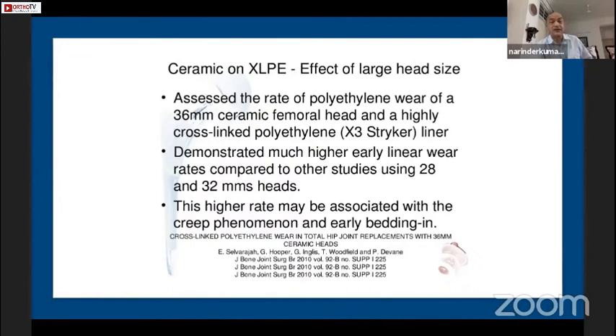This is showing that 36 mm actually has an accelerated poly wear rate, the higher rate as compared to 28 and 32 mm. So be careful when you're using large heads in that thin poly liner.